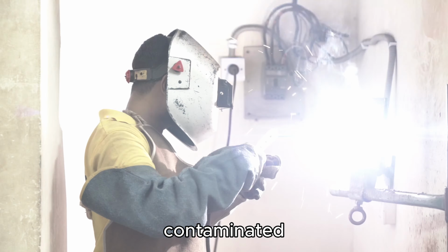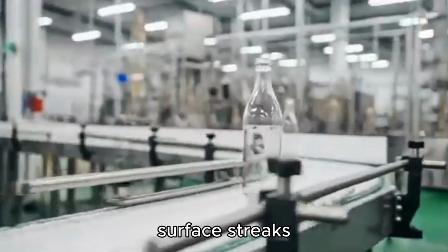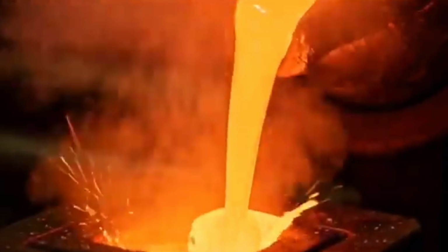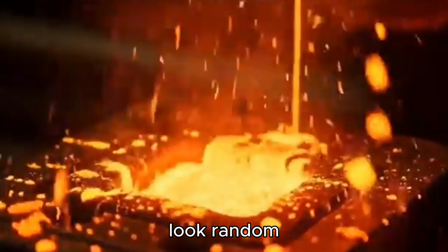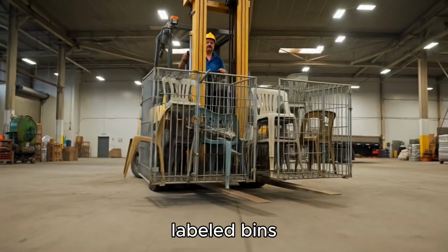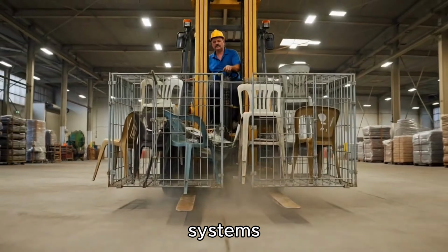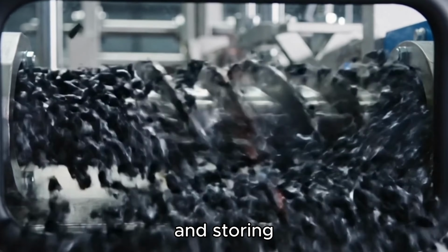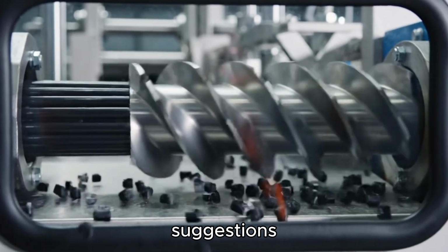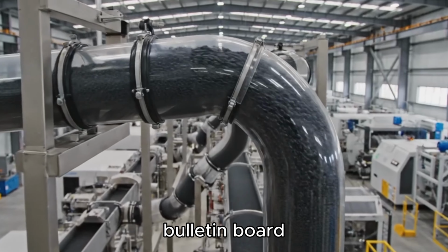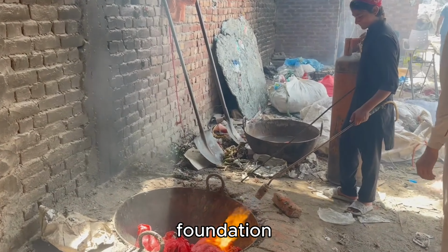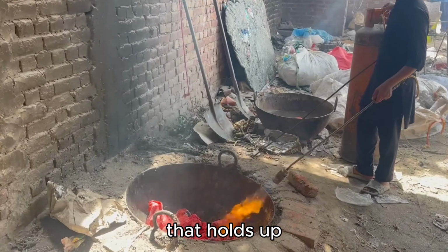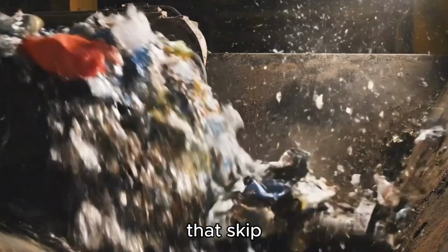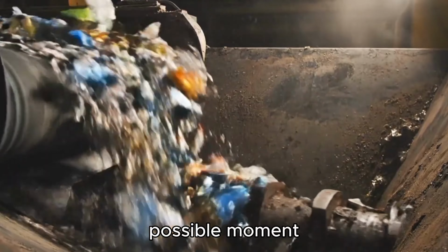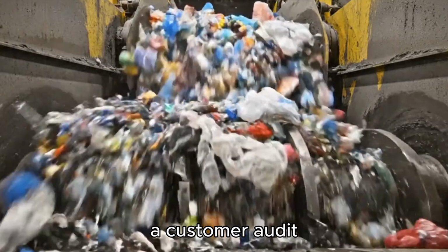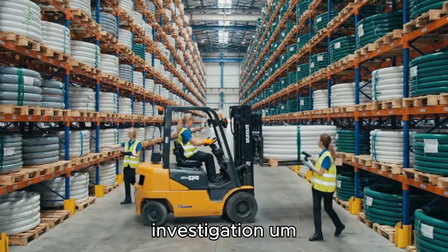In injection molding, contaminated regrind shows up as surface streaks, layer lines, discoloration, and parts that crack in ways that look random but aren't. Dedicated labeled bins, color-coded collection systems on the floor, granulating and storing by material type. These aren't suggestions that get posted on a quality bulletin board. They're the operational foundation of any regrind program that holds up over time. The factories that skip this step tend to find out at the worst possible moment, usually during a customer audit or a product liability investigation.